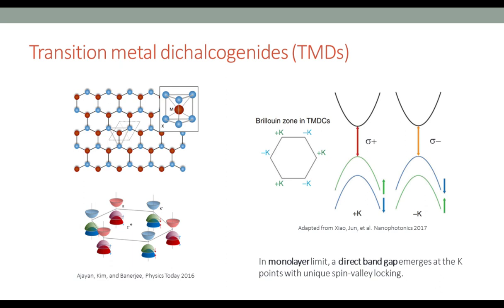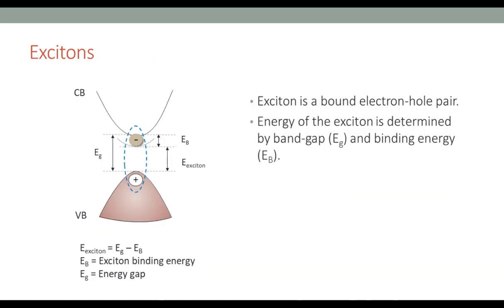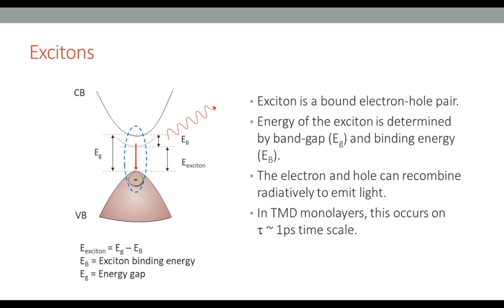But to go back, what are excitons? Excitons are a bound state that arise when you have an electron-hole pair. In this case, we can excite an electron out of the valence band into the conduction band. And if the binding energy is strong enough, then the electron-hole pair bound state will form an exciton. But since this is an excited state, the electron will recombine, and so this has some characteristic time scale. In the TMD monolayers, this recombination time tends to be about 1 picosecond.